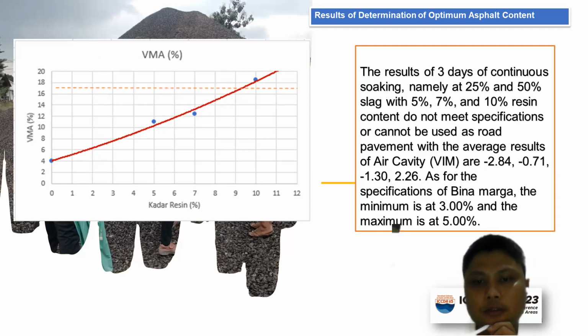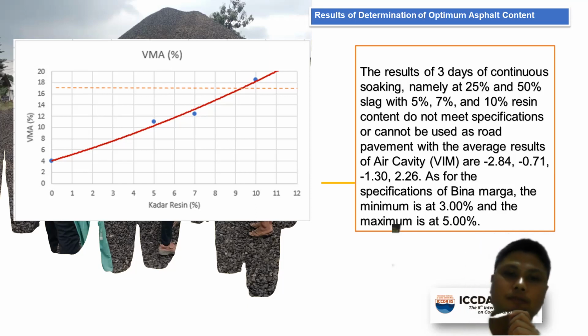with the average result of air cavity void in mineral that means minus 2.84, minus 0.71, minus 1.30, 2.26. As for the specification of Bina Marga, it is 3% until 5%.